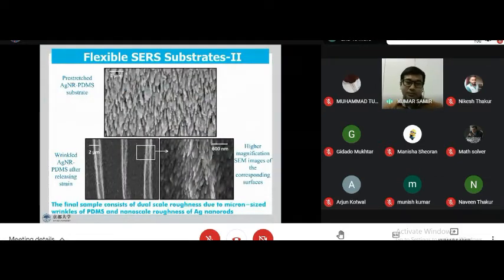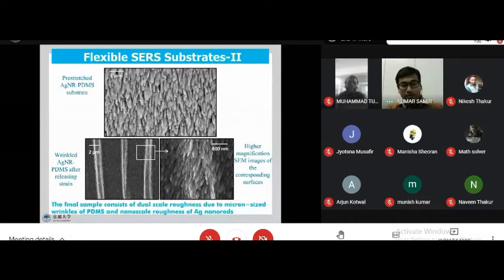So this is the SEM image of the pre-stressed silver PDMS, and after releasing the strain, these kinds of wrinkles are formed. The amplitude of these wrinkles is around 2 to 3 micron, which is equal to the size of the bacteria that we have utilized. Our main purpose was to capture the bacteria within this region, so that it will touch the bacteria from the sides also.